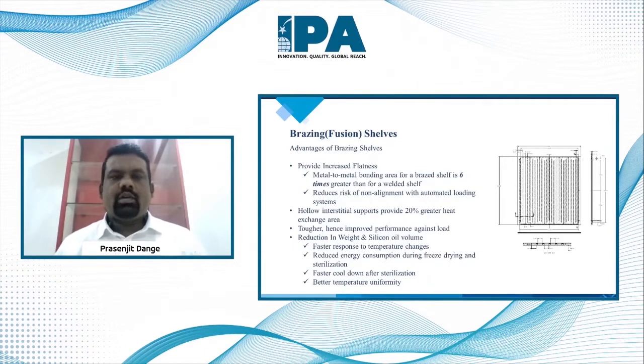So if we talk about the advantages of the brazing shelf, there are many advantages associated with that, like increased flatness for the shelves. Basically, there is a hollow structure which has a metal to metal bonding area that is much better than the welded shelves, almost six times better. And since it's a hollow structure, you can put more baffles in the shelves, which gives tougher, stronger shelves, and it reduces the risk of non-alignment because of that.